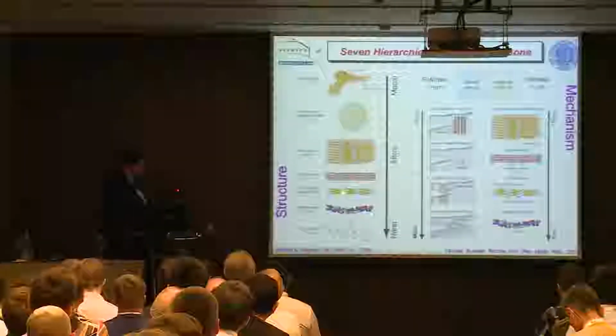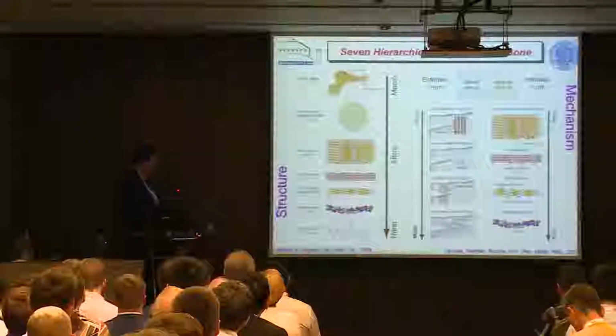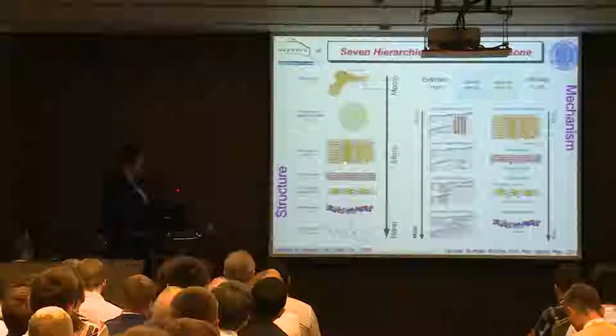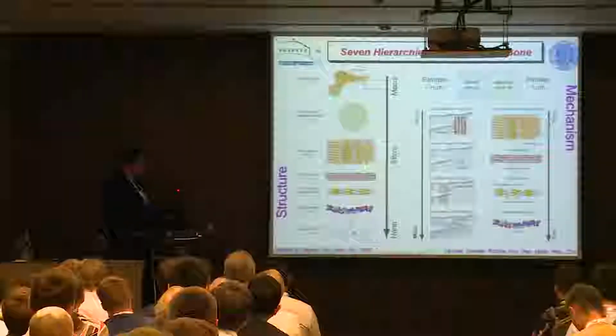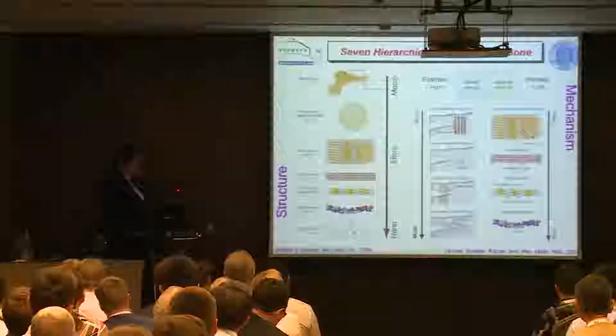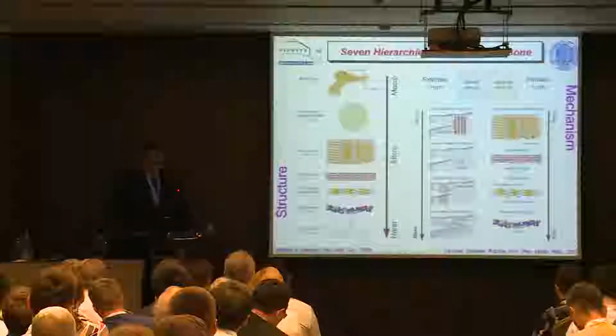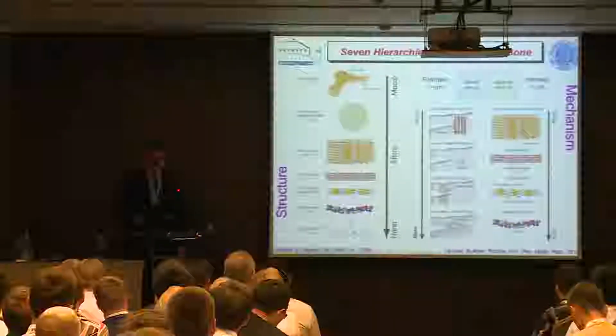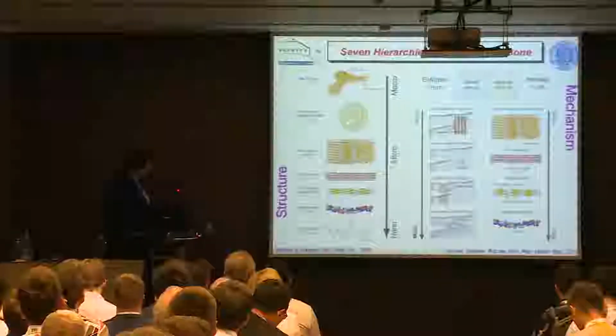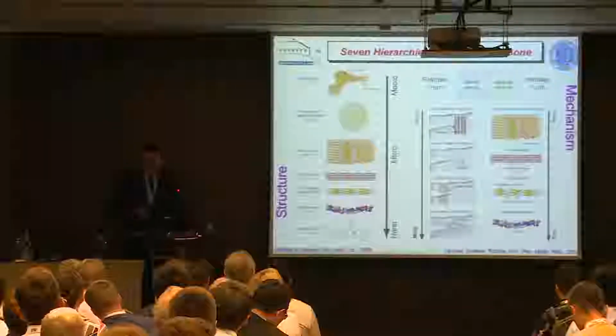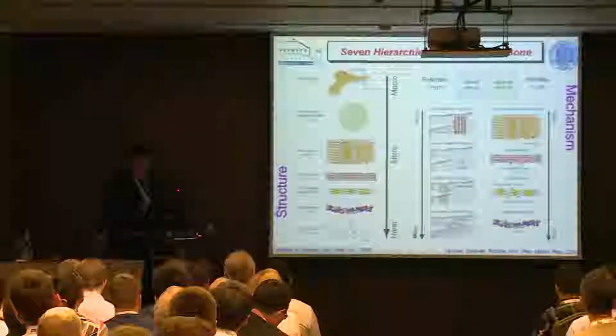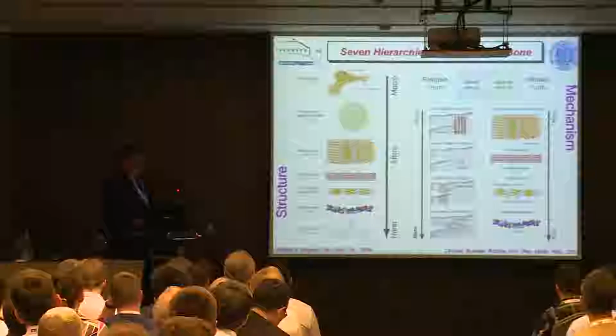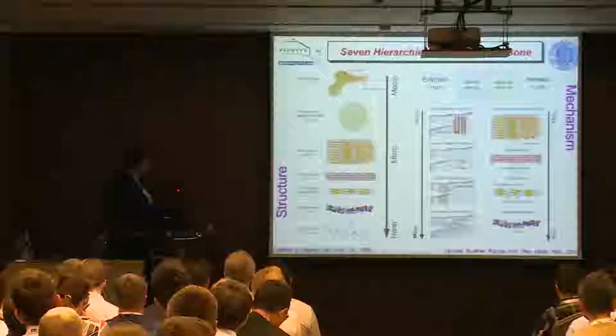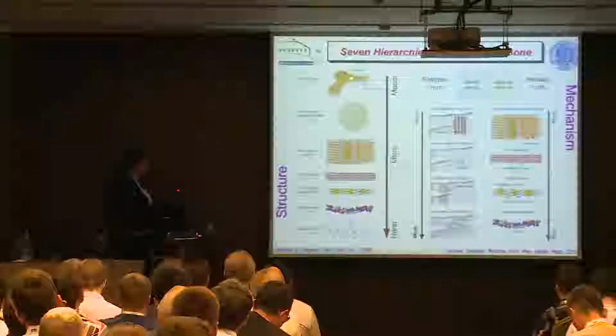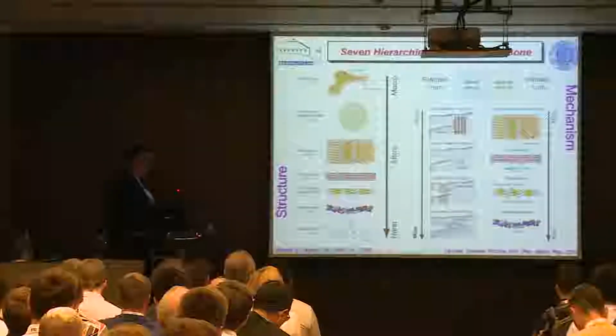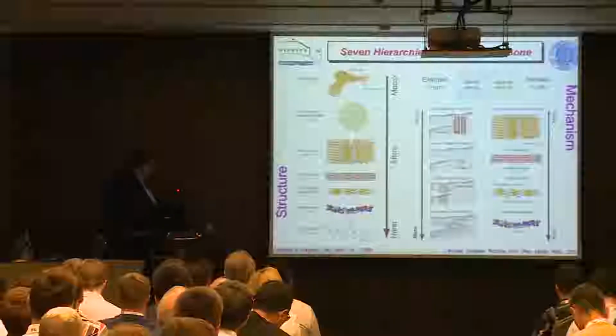These are the fibrils. The fibrils then are twisted into fibers. We're now up into what's sometimes called the lamellar bone regime. We're in the tens of microns now. And then we go up into the hundreds of microns, and we have these so-called osteons, which contain the Haversian canals. These are concentric structures. The interior carries the blood vessels, and the bone remodels that way. And this has characteristic length scales of hundreds of microns. And then up at the top here we have the bone itself, and of course there's the compact or cortical bone on the outside, and the trabecular or spongy bone on the inside. So it's a whole range of length scales.